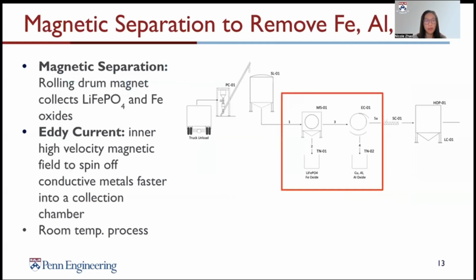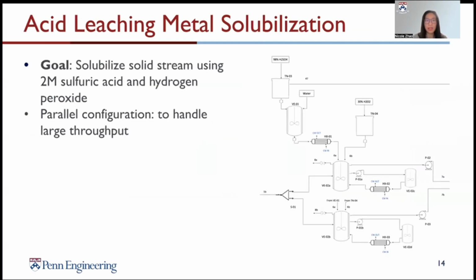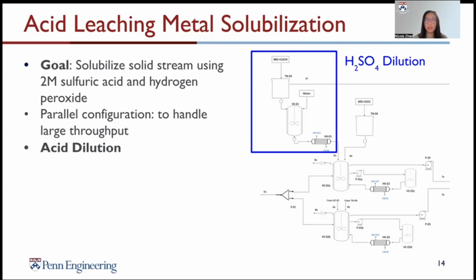The first step is the solids removal step, where magnetic separation is utilized to, one, collect lithium iron phosphate, which is a battery cathode material, with iron oxides, and two, an eddy current step that collects copper, aluminum, and aluminum oxide. The acid leaching step utilizes 2 molar sulfuric acid and hydrogen peroxide to solubilize the solid stream. A parallel configuration is utilized here to handle the large throughput of our process, along with the acid dilution step that takes 98% sulfuric acid down to 2 molar or 17% sulfuric acid.